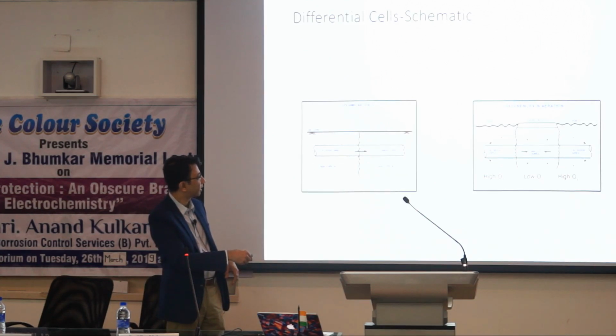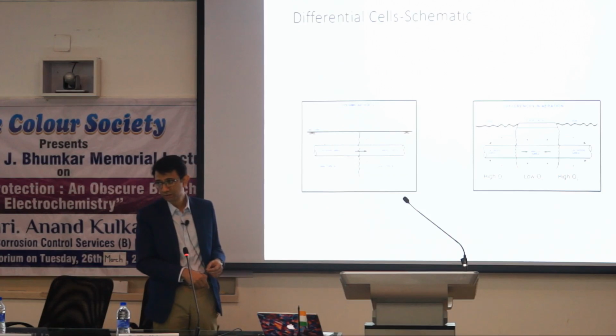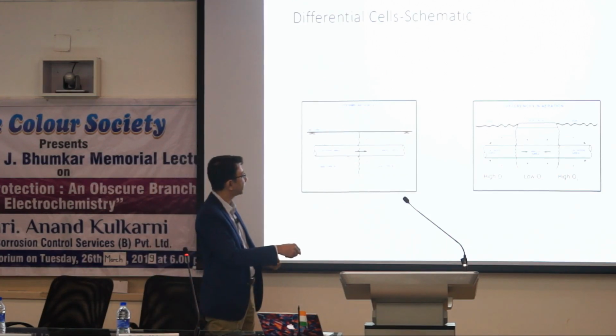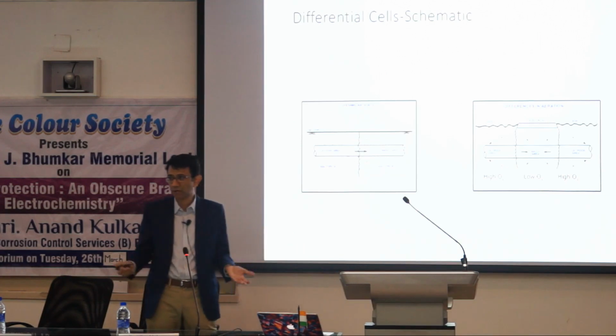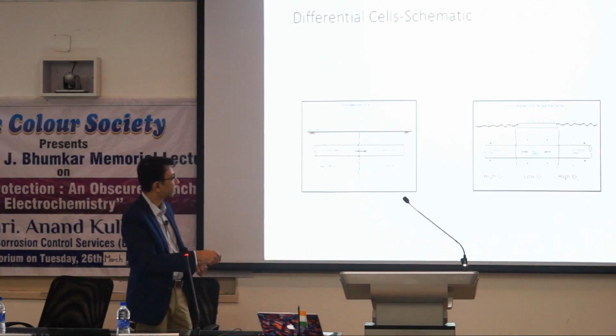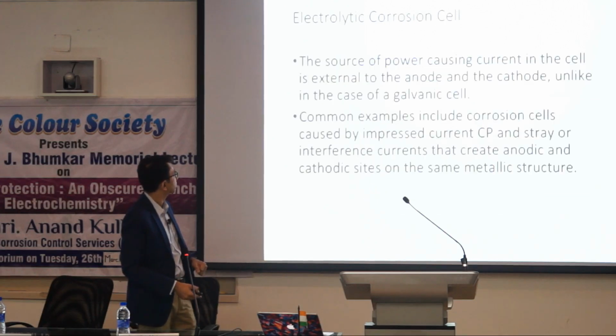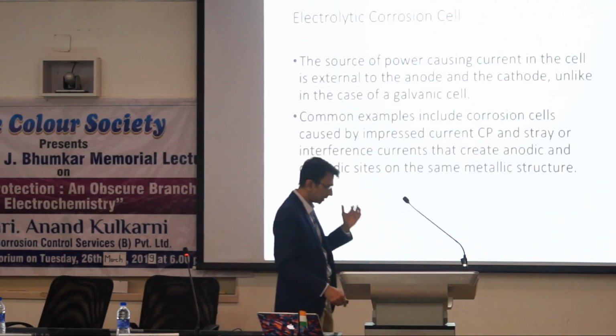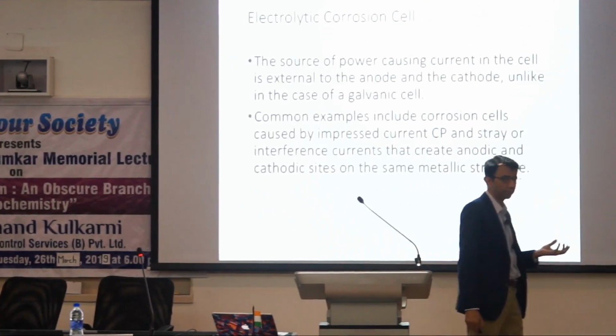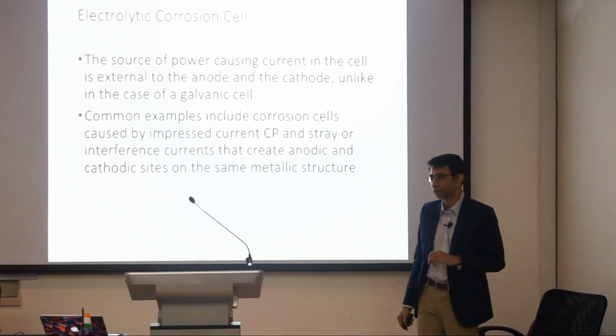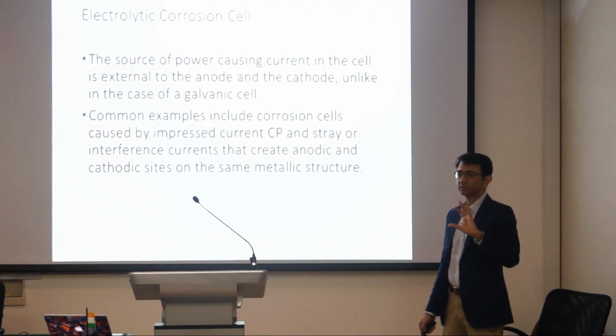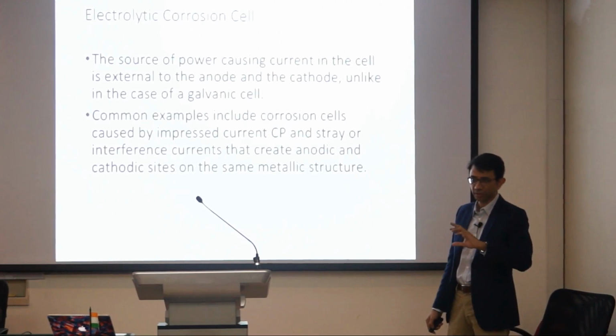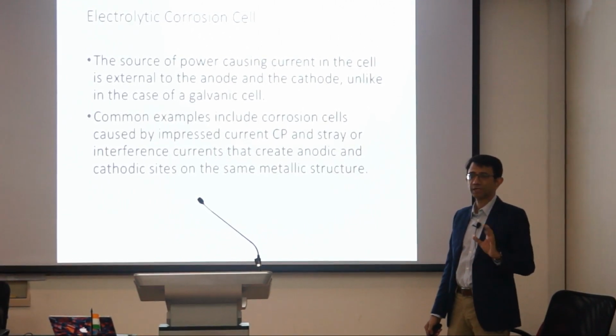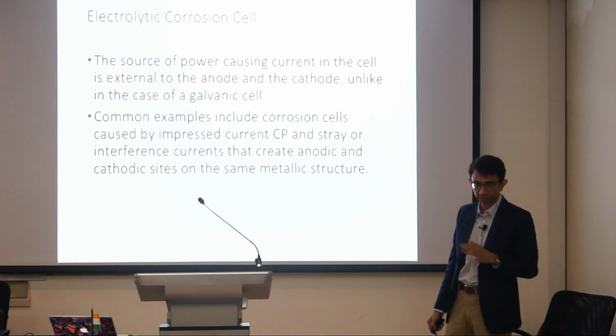and so you would have this area corroding and this area getting protected because the low oxygen impels electrons to flow towards the cathode for the reduction reactions. And we find that oxygen being a cathodic reactant, wherever you have high oxygen content, that area becomes the cathode. So this is a galvanic cell, and the galvanic cell is obviously the result of a difference in potential, a natural difference in potentials. And so we find that the natural difference in potentials is attributed to having dissimilar metals or dissimilar conditions surrounding the same metal, which is what we've just seen.